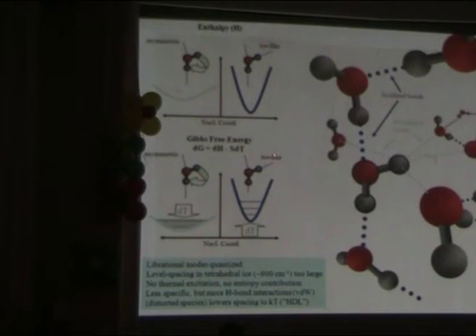They will not contribute to the entropy. If we break hydrogen bonds, the molecules become freer to rotate. The potential energy surface comes down, becomes flatter, the level spacing comes down, and we can now thermally populate these levels. And there we have a contribution to the entropy.